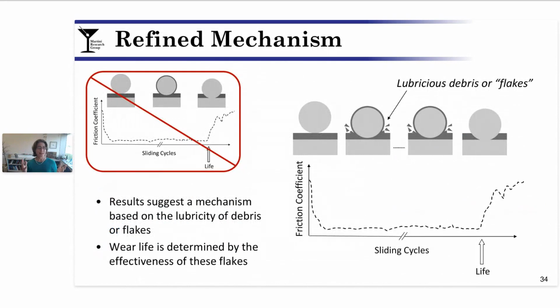So taken together, this kind of disrupts the simple mechanism that I started presenting you with, right? We talked about a long wear life followed by failure when the coating was gone. The results I've shown you here, along with multiple others in the literature, support a slightly more complex mechanism, where during these initial stages of sliding, and perhaps throughout sliding, debris or flakes are generated. And these are helpful.